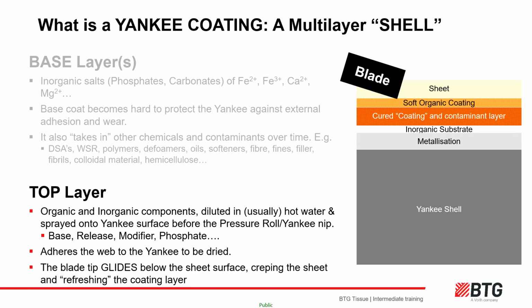Because the sheet is still 60% moisture at the nip, this water contains residual pulp contaminants and process and functional chemicals which will also be taken into the coating. How much is taken in depends on the efficiency of the chemical and the solids equilibrium management by the machine. Most of this, over time, ends up in the hard cured coating layer.